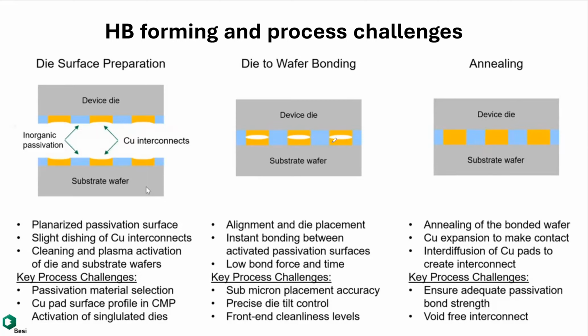Remember, this initial contact is done by van der Waals force. And here it becomes covalent bonding, which is quite strong. As long as you ensure that the bonding is very covalent, as close to the theoretical value as possible, then you're fine. And that is the bond strength, okay? And then you would like to have it void free, of course. That's the ideal world. Whether you get that, that's a different story, right?